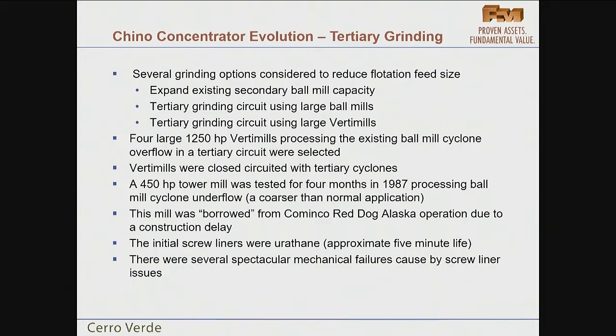We had some comfort with the Verti mills because in 1987, we had tested a 450 horsepower tower mill at Chino. This was borrowed from the Cominco Red Dog operation in Alaska, which was on a construction delay and was taking up space in the Metso parking lot in York, Pennsylvania. So a deal was worked to allow us to test this thing. We installed it and ran ball mill cyclone underflow through it. Not overflow, underflow, relatively coarse material.